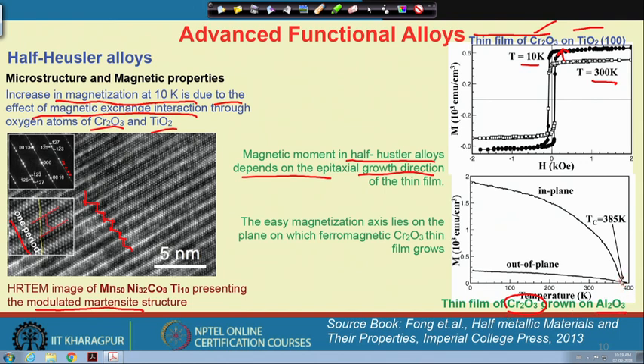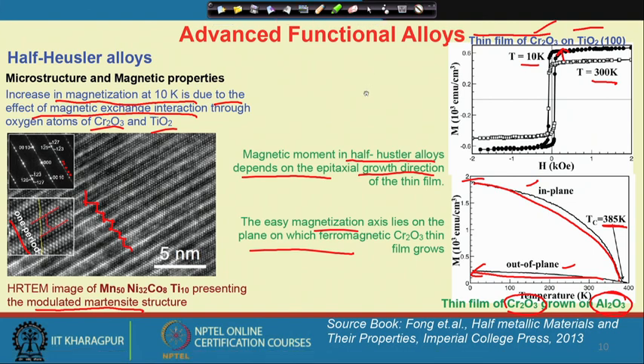So, let us say here it is around 385 K, where out of plane and in plane refer to whether we are measuring this axis in the plane of alumina or out of the plane. The difference goes higher. Okay. So, the magnetic moment in plane is much higher than out of plane, and these are very typical features of such half Heusler alloys in terms of magnetic properties.